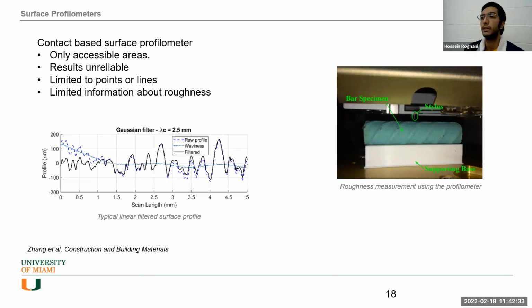There are several equipments and several approaches that can help you to characterize the surface of your materials, in this case the rebars. The first one I can mention here is the linear contact-based measurement, which is the typical measurement system, and only provides measurement data on the areas that they are able to contact, because the probe tip should contact your specimen. Measuring the specific locations where to put the probe makes the result unreliable, because there are some places that you can put your tip on and there are some places that the roughness is very small, so the result really depends on the tip. And also the data is limited to the points and the lines, and that's the main problem with this linear contact-based surface profilometer.